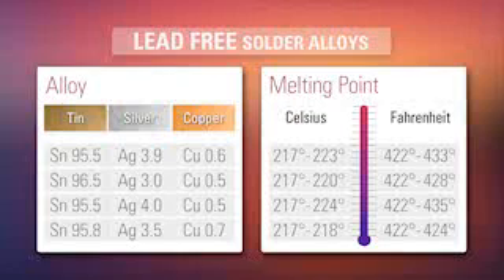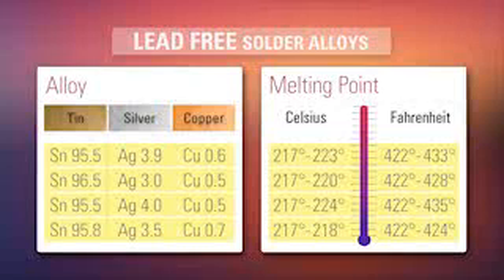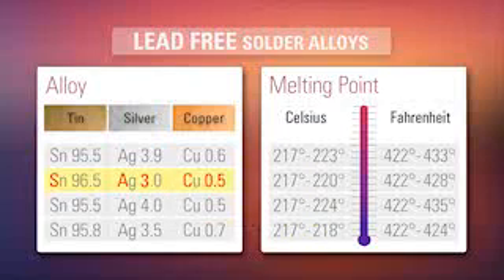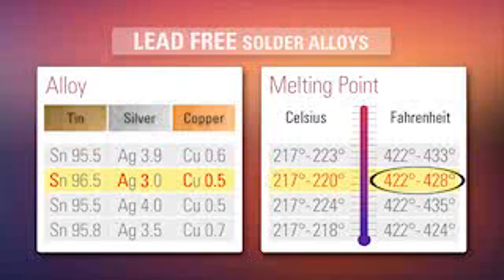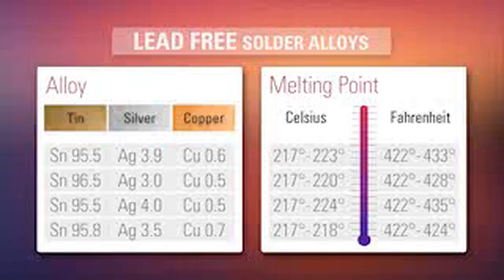Now, let's turn our attention to lead-free solder. There are many different types of lead-free solders available today, so it's important to note that they will all have different melting points. The most common lead-free alloy for hand soldering applications consists of tin, silver, copper. One common tin-silver-copper alloy is called SAC 305 and contains 96.5% tin, or Sn, 3% silver, or Ag, and 0.5% copper, or Cu. SAC 305 begins to melt at about 217 degrees C, or about 422 degrees F, which is 34 degrees C higher than tin lead. SAC 305 solder has a plastic phase of about 3 degrees C, or 6 degrees F. Your company will select the specific lead-free soldering alloy you will use for hand soldering applications.